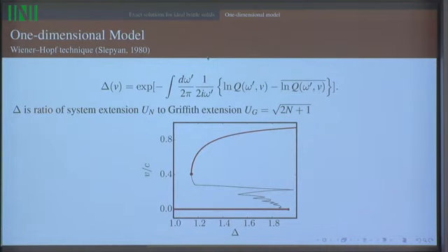The nature of the process is one, and this is literally true only at 0 temperature, but I still think even at our normal room temperatures for brittle materials, it captures the essence of the materials. The atoms don't want to permit the solution to exist when the velocities are below a certain critical value. Hence a tendency always for the crack to sit stationary, trapped, and then to figure out eventually, after lots of trials, typically driven by thermal fluctuations, that there's this dynamic branch up here, and then immediately rushing to a fraction of the sound speed and rushing along. So although this is a simple model, and although there are all sorts of caveats that one could express, I think that this inadmissibility of all the low velocity solutions is actually capturing one of the essential qualitative features of brittle fracture that we've known about since we regretted dropping a glass of milk.